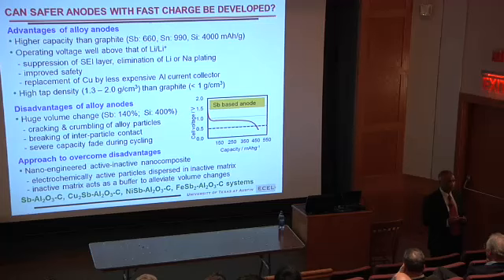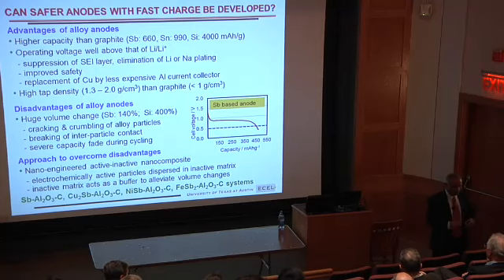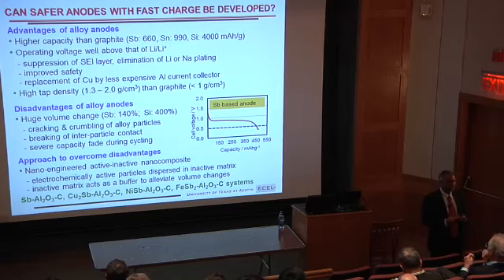One electrode will be 1 millimeter thick, another electrode will be 1 micron thick. I mean, not 1 micron, maybe 10 micron. So with the cathode capacity right now, anything above 700 milliampere hour per gram of anode capacity is not going to make any big difference.